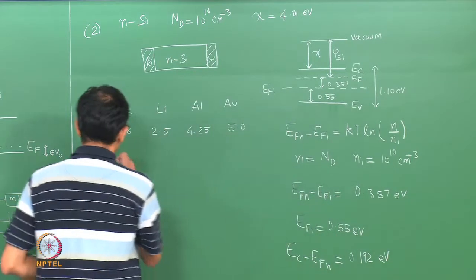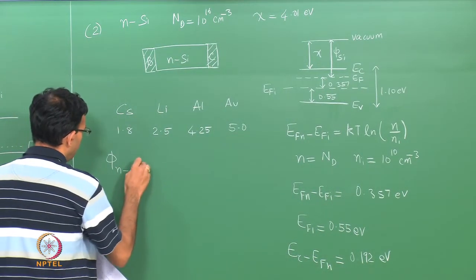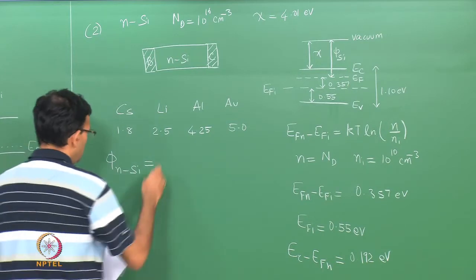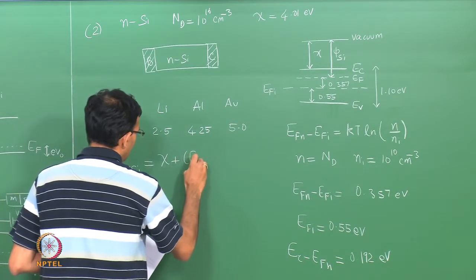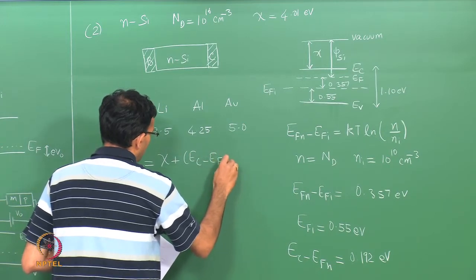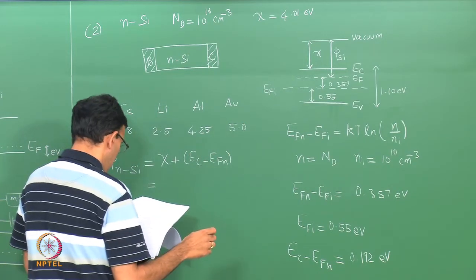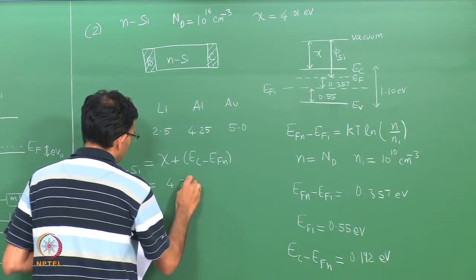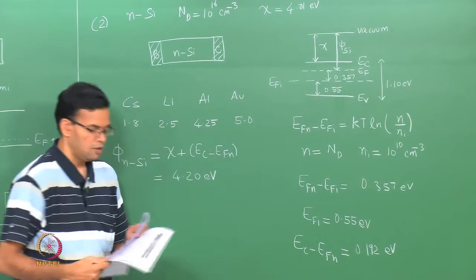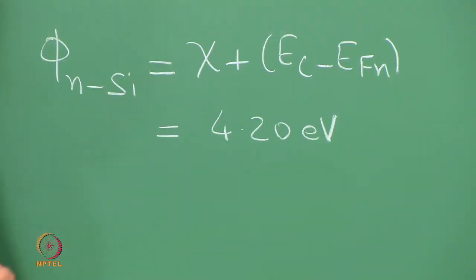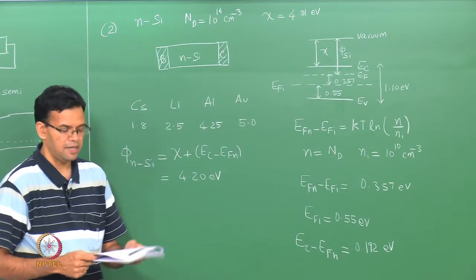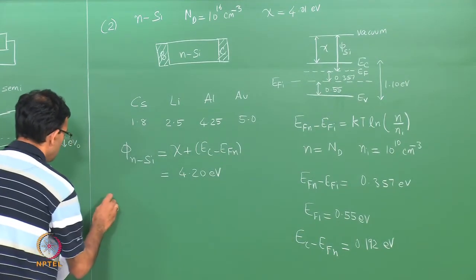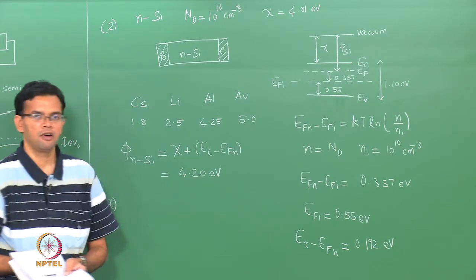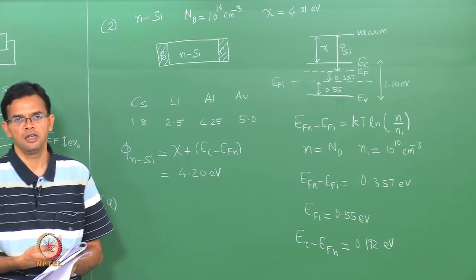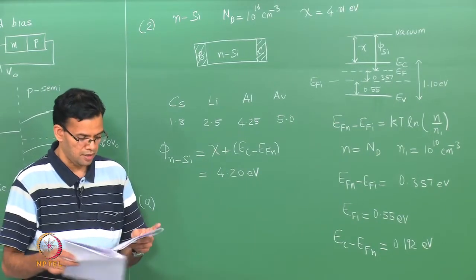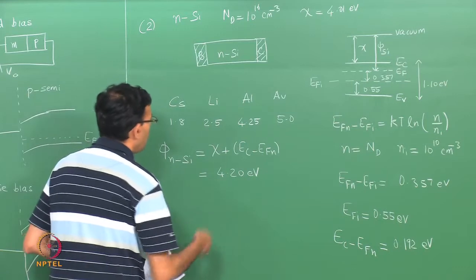So, phi of silicon, since it is n type I will just write phi of n, is nothing but chi plus EC minus EFn, which works out to be 4.20 eV. So, if you look at the various parts of the question, part A asks which metals will result in a Schottky contact. So, we have a Schottky contact when the work function of the metal is greater than the work function of the semiconductor. So, those are essentially aluminum and gold.